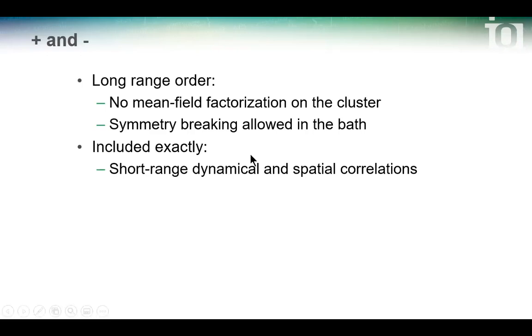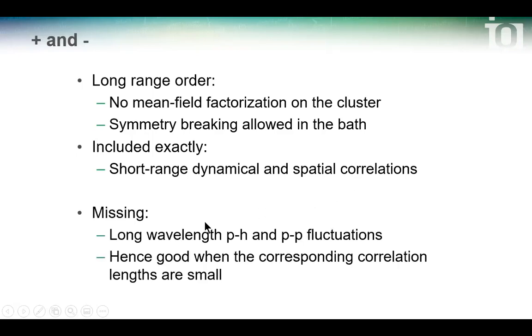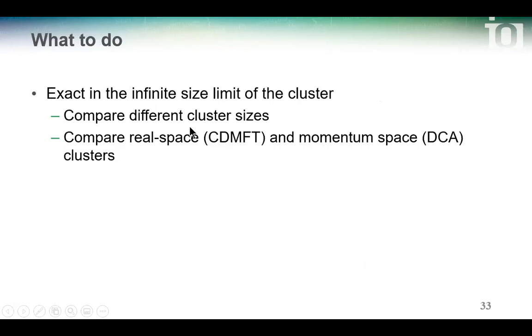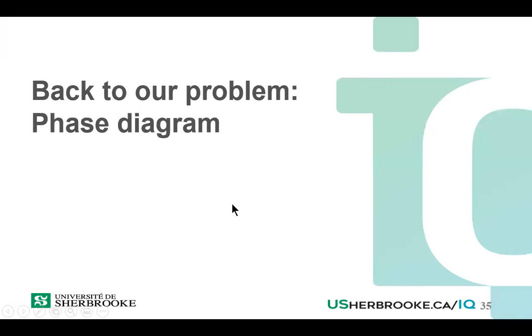And what's included exactly is the short-range dynamical and spatial correlations. What's missing are the long wavelength particle-hole and particle-particle fluctuations. And it's good when the correlation lengths are small. So what to do: it's exact in the infinite size limit of the cluster, so you compare clusters of different sizes. And you can compare real space and momentum space clusters. Okay, back to our problem. Do you have any questions on the method?